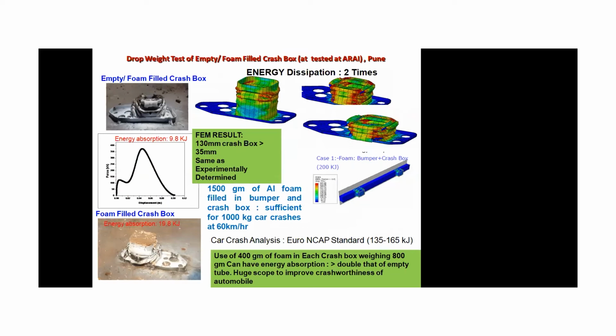We have also got a facility for simulation. So we have simulated the crash boxes used in automobiles, without foam and with foam, and we have also tested them under real conditions. We put the crash box under a machine and did crash analysis, and we measured the energy absorption. We found that the empty crash box made from steel absorbs about 9.8 kilojoule, but if you fill it with foam, it can absorb 20 kilojoule.